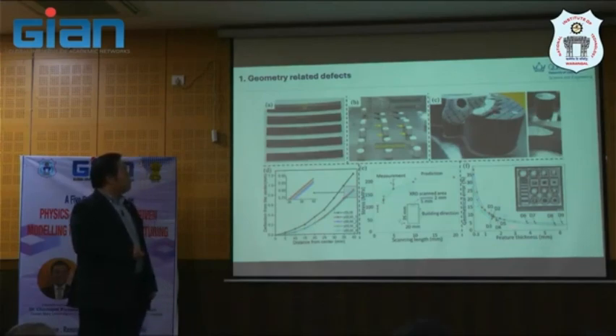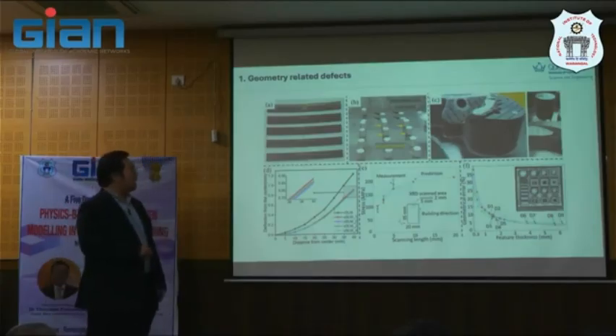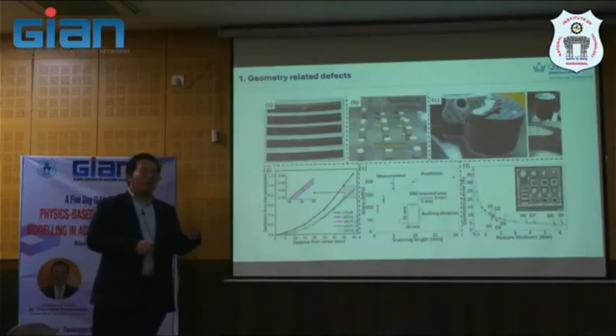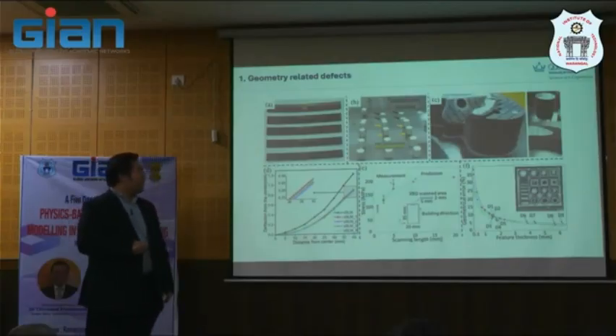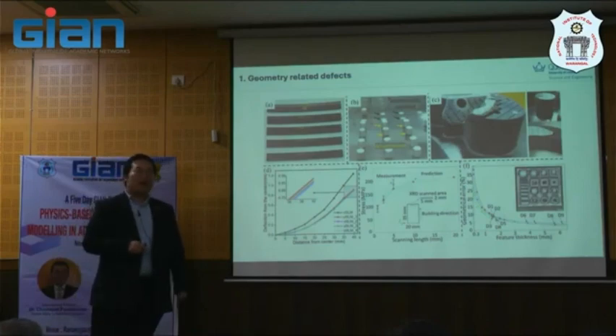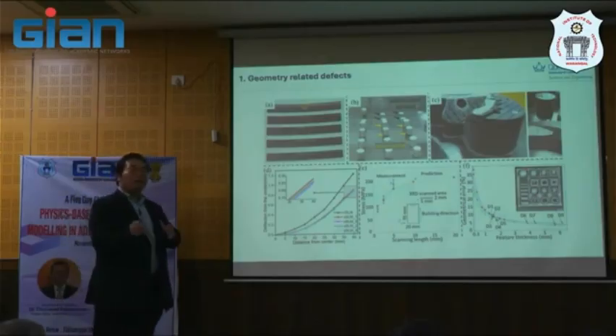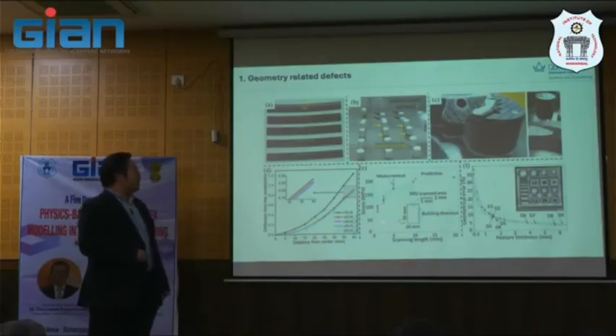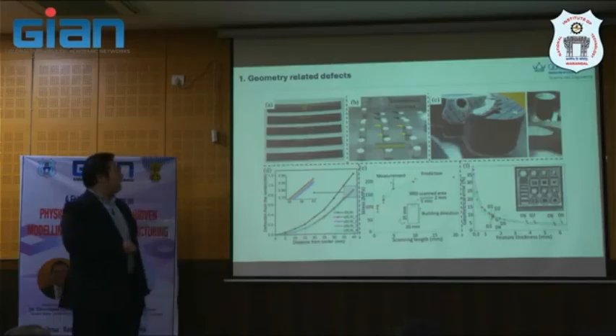So people are trying to correct or systematically investigate how features of the thickness contribute to the geometrical error that I showed you in the last two slides, where they compare between the CAD model and the printed model and try to see what the mismatch is. And you see the error is actually quite significant. It can be up to 35% mismatch or deviation from the geometry that we want to print. And this contributes, as I said, if you print something quite long compared with the base material here, you get some bending, or you can measure the stress and also try to predict it. And this is the geometry-related defect that I tried to describe before.